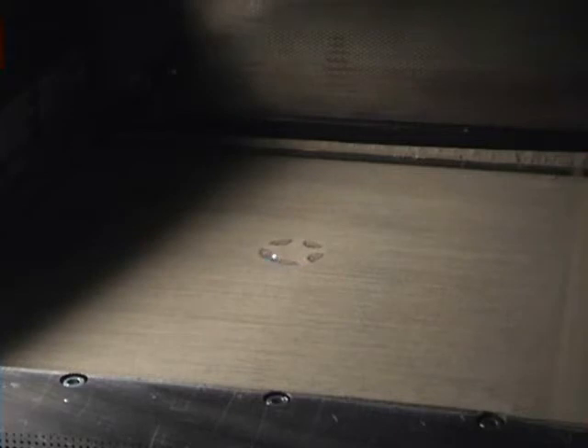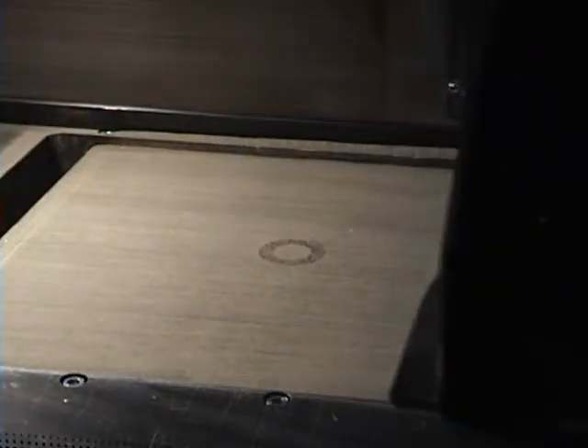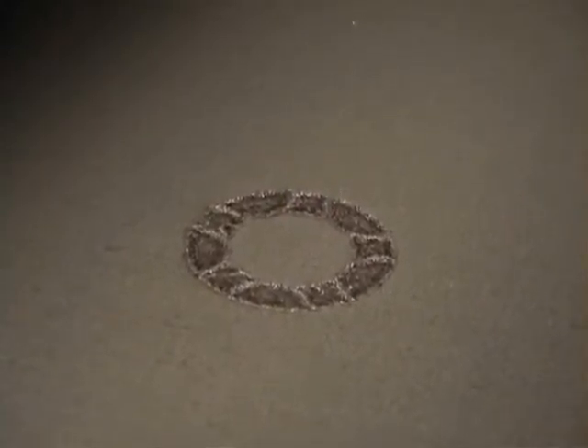The usable build area is 9.5 inches by 9.5 inches by 8.5 inches. Each layer thickness is between 0.001 and 0.004 inches. The machine operates a 20-watt laser with a fine focus diameter of 0.004 inches. This gives excellent resolution to parts. This part is being created with a powder called Direct Metal 20, which is bronze-based. Other materials offered with the DMLS process include stainless steel, cobalt chromium, and titanium.